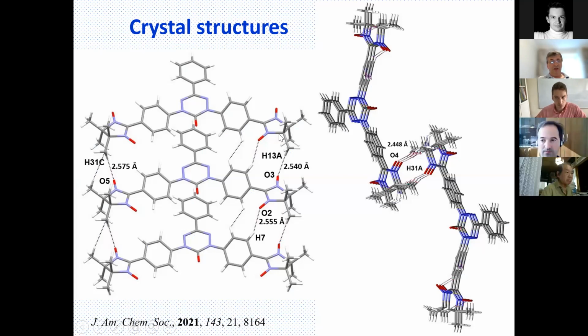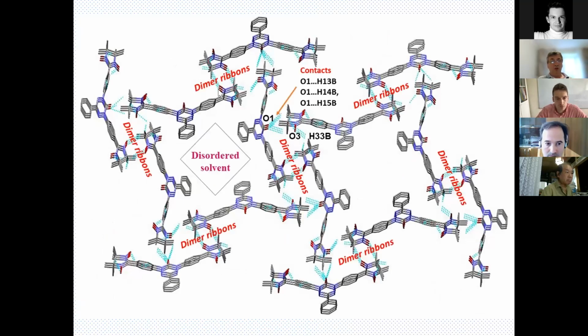This triradical forms short contacts between the oxygen atom of the nitronyl nitroxide group and a hydrogen atom of the phenyl ring. These contacts bring molecules into a ribbon, and then we have inter-ribbon contacts which form so-called dimer ribbons. These dimer ribbons are linked via a short contact between the oxygen of oxo-verdazyl and a hydrogen atom of the methyl group into a 3D structure having some space filled with disordered solvent, in this case acetone.